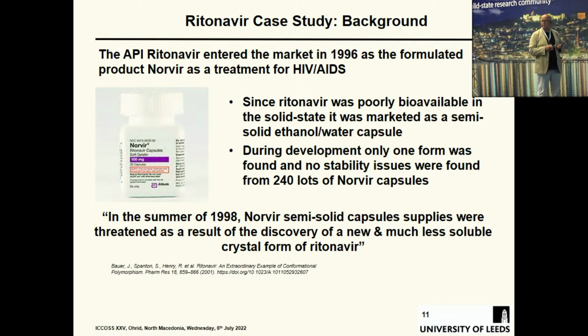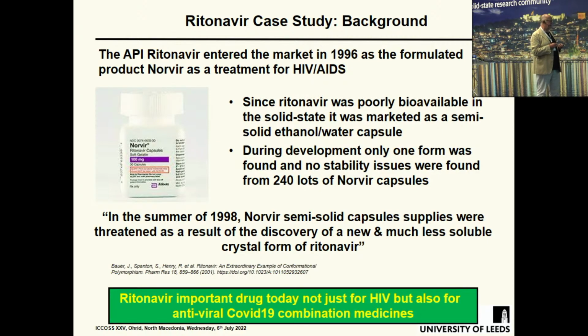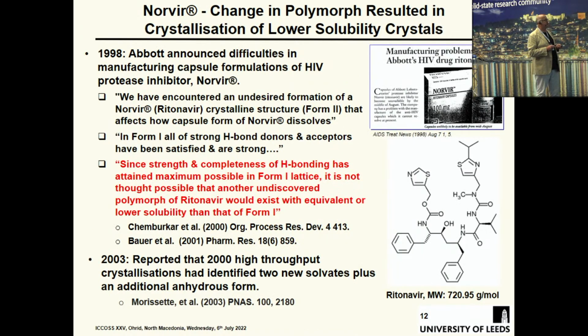They did a solid form selection, they found the stable polymorph, or that's what they thought, and they tested it, as you do, by making lots and lots of batches and doing lots and lots of testing. And basically, around 1998, there was a big problem. They were threatened as a result of a new and much less soluble form of ritonavir. It's important to note that ritonavir is an important drug today, not only as an antiviral for the dreadful AIDS epidemic of the 90s, but more recently in combination medicines for COVID-19, and that's formed quite an important medical treatment for COVID. So this was the original press release that came out.